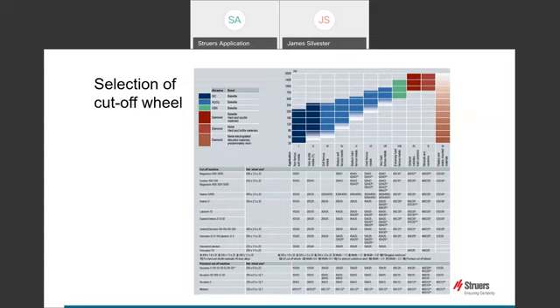The selection guide is intuitive, and we generally aim for your material to be somewhere near the middle of the cutting wheel capability range. For example, if we choose a medium hard steel, which can be found in material group 5, the typical wheel range we aim for has a hardness between 170 Vickers and 520 Vickers. If this meets the criteria for the material we are cutting, the column directly below this tells us which cutting wheel would be the best option to choose. When we know what material class column we need, we can trace this column down to match up with either the machine that we're using or the wheel size we need.